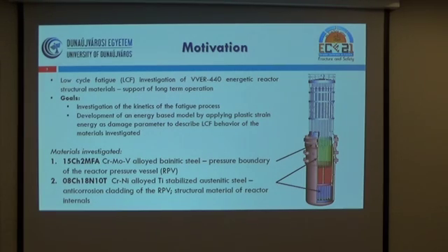We investigated 2 types of materials. One is a chromium-molybdenum-vanadium alloyed bainitic steel, which is the pressure boundary of the vessel, and the other one is a quite well-known chrome-nickel alloyed, titanium-stabilized austenitic steel, which creates the anti-corrosive cladding of the reactor pressure vessel, and this material is the structural material of all the reactor internals.